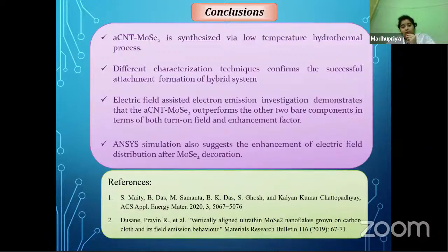Finally, we come to the conclusion that our heterostructure is synthesized via a low temperature hydrothermal process. Different characterization techniques confirm the successful attachment or formation of the hybrid system. We measured the electron emission phenomena for the three samples, and it is confirmed that our heterostructure performs best in terms of both turn-on field and enhancement factor. Also, the ANSYS simulation suggested that the electric field distribution is much better in the composite heterostructure than in amorphous carbon nanotube.